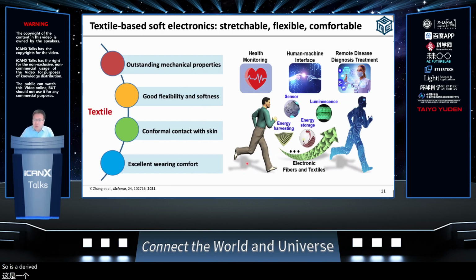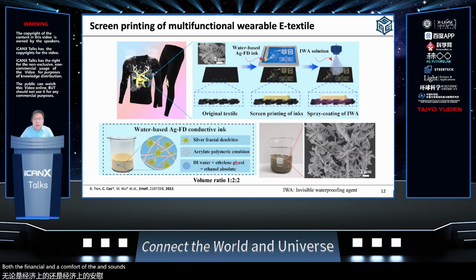So it's desirable to develop new smart textiles that can integrate both the functionality of electronics and the comfort of textiles. We developed a screen printing process to deposit a water-based conductive ink on the textile surface with a pre-painted mask. After printing, we also need an invisible waterproofing layer on top to protect against cracking. The water-based conductive ink was made of silver fractal dendrite and a transparent binder, with a mixture of solvents, EG and EA.